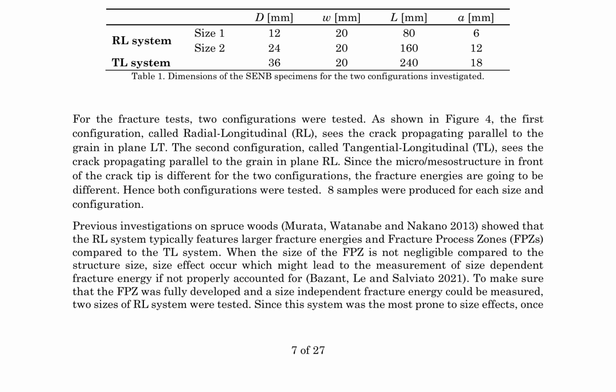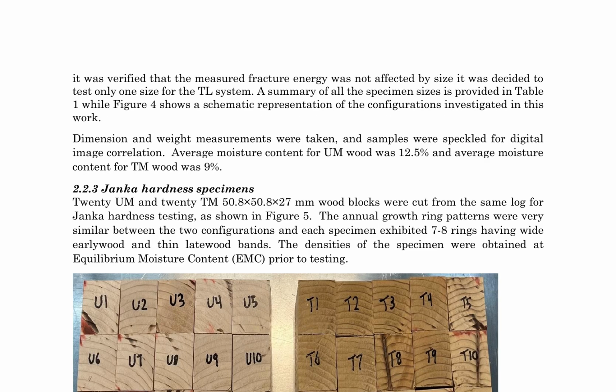The testing of both configurations is necessary due to differences in mesostructure in front of the crack tip, resulting in disparate fracture energies. By investigating both configurations, this study aims to provide a comprehensive understanding of the fracture behavior of wood samples, encompassing the effects of configuration and size on fracture energy and FPZ. The experimental setup involved testing a single size of the TL system, as the measured fracture energy was found to be unaffected by size. A comprehensive summary of all specimen sizes is presented in Table 1, with a schematic representation of the configurations examined in Figure 4. Dimension and weight measurements were obtained, and samples were speckled for digital image correlation analysis.